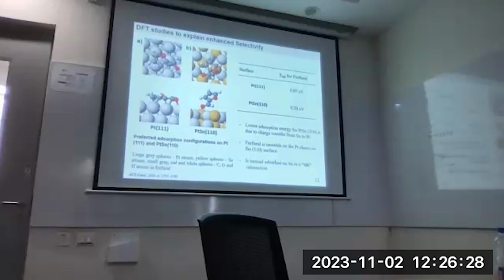So the affinity for hydrogen adsorption was done with pure hydrogen. And how well will that translate to hydrogen associated with the molecule? You are measuring whether the tin and platinum both will take up hydrogen, right? That experiment you did by sending hydrogen. What we do is we put the catalyst in the reactor, and then we pass the hydrogen over it. Here I'm not showing the hydrogen, but it's mostly only this molecule. The assumption is that when the hydrogen comes, it has to go on the platinum. The hydrogen will adsorb only on platinum.